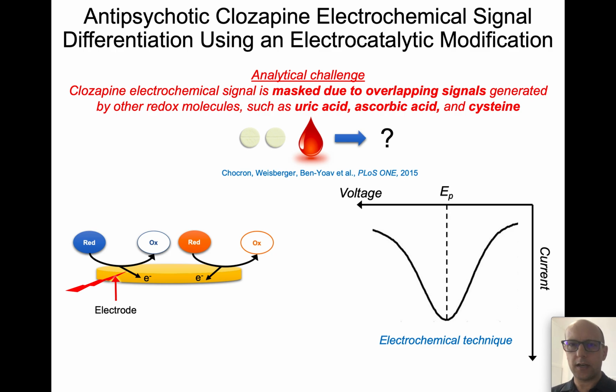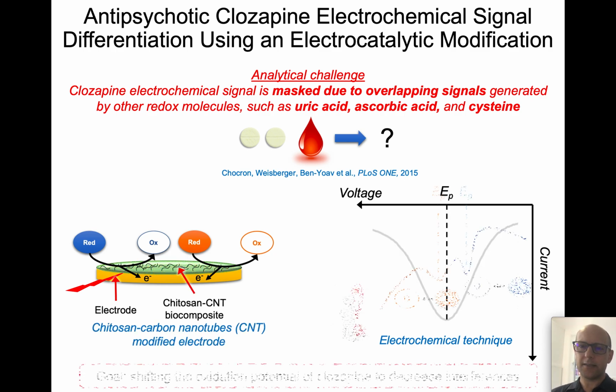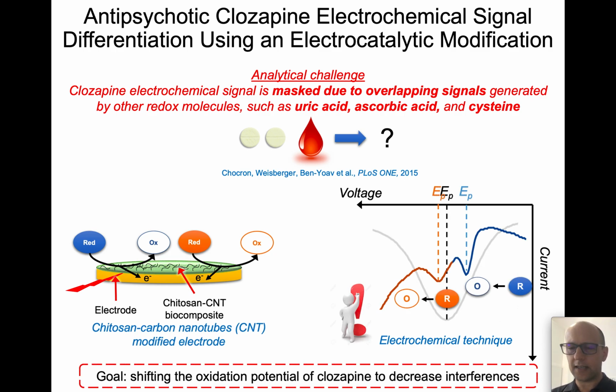So previous work showed that the main masking and overlapping signals are uric acid, ascorbic acid, and cysteine as the interfering molecules. Our approach is that by modifying the electrode with electrocatalytic material, carbon nanotubes encapsulated in the biopolymer chitosan, we could have an electrocatalytic effect on some of the redox molecules that will shift or decrease the activation energy and shift the potential peak of some of the molecules, revealing the signal from the clozapine and improving the detection performance.